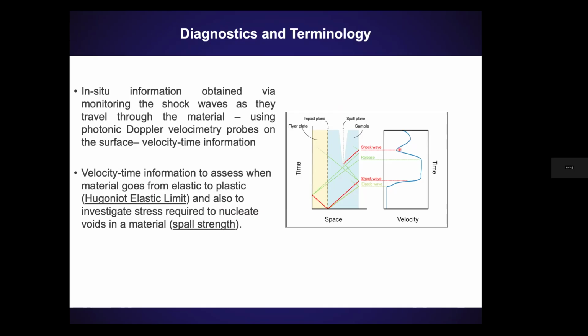You can use this free surface velocity plot to also calculate the stress required to nucleate voids. Again, that's an approximation. Basically, you can look at the difference in velocity between here and the top point and convert that using the bulk sound speed and density of the material into a stress required to nucleate voids. That gives you an idea if I make a material using additive manufacturing versus conventional manufacturing, does that really affect the spall behavior of the material?